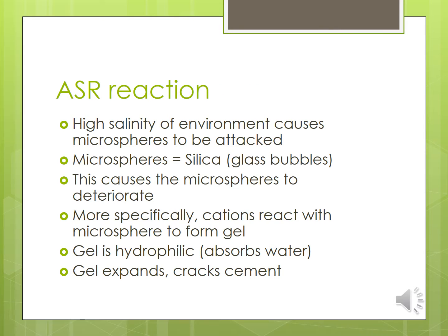So basically, the biggest problem with mixing low-density cements with microspheres is the ASR reaction. What happens during the ASR reaction is the microspheres deteriorate because they're in a high salinity environment. The high salinity environment attacks the microspheres and causes a gel, and that gel is hydrophilic, and a hydrophilic gel absorbs water, and whenever it absorbs water it expands, and whenever the gel expands it cracks the cement.